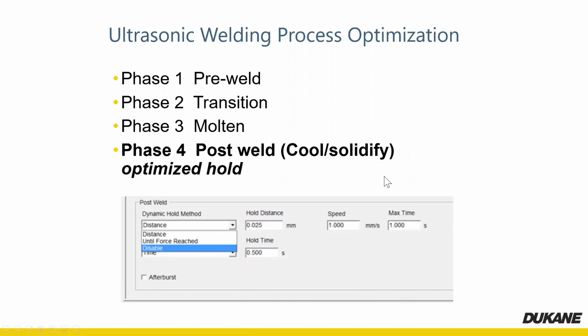Now we get into the last part of this, which is the post weld. So we're talking about hold here, and sorry about the phone ringing in the background. In post welds with a pneumatic welder, again, it's always dynamic. You're always squeezing plastic. You're always compressing. You're always collapsing. With servo, we can stop. So we've basically broken our weld into 2 portions. We've got our dynamic hold, and in this instance we've disabled it, but you can still hold and collapse for a small amount of collapse distance.